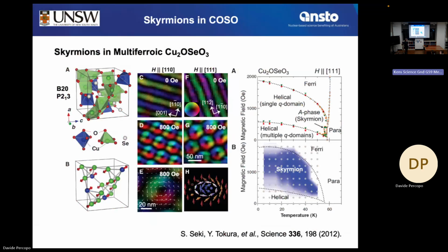That's the phase diagram. And we have, at zero magnetic field, a helical spin arrangement. And if we switch on a small magnetic field, we see the skyrmions. In a single crystal, just in that very narrow temperature range, and in thin films in a broad range.